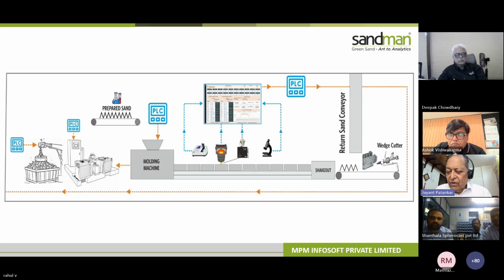Thank you, sir. The use of borings in the melt has a twofold side effect. One is the higher power or energy requirement, as mentioned by Rahul. And second, because every particle we add acts independently, the burning losses are higher. So you have a very serious problem of carbon drop in the melt, and you have to calculate your charge. Recarburizers will be an additional material that has to be calculated. So first make the calculations of the requirement and establish the losses from the process of melting turning borings and fines. Once that is done, every other process is the same as explained by Rahul and referred to in the chart in front of us right now.